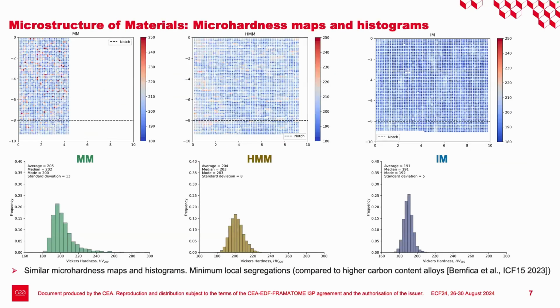Okay, so we have started to make some microhardness maps just to check whether there would be some chemical segregation in the material that would be revealed by local points of higher microhardness. Basically, we didn't find any large segregation area for all the materials. Maybe the first model material has a larger standard deviation, but it's quite okay. They have more or less the same properties in hardness.